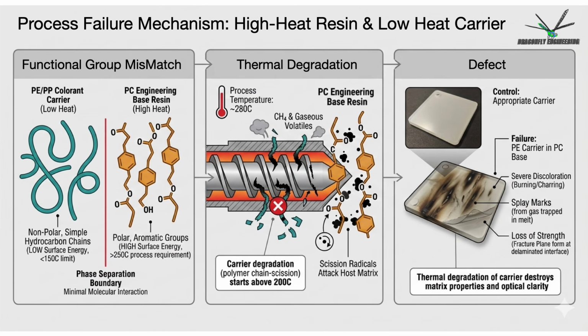The outcome is really not good in that you have aesthetic issues and you're also going to have structural issues. Those trapped gases leave silver splay marks or maybe something like a diesel mark across the molded part. You could get some charring, just depending on how high the temperatures get inside the extruder and inside the mold. And that's from the unstable carrier. And this could cause black burning and discoloration. You could also get mechanical failure in the form of delamination, like fractured planes, destroying the impact strength and optical clarity.